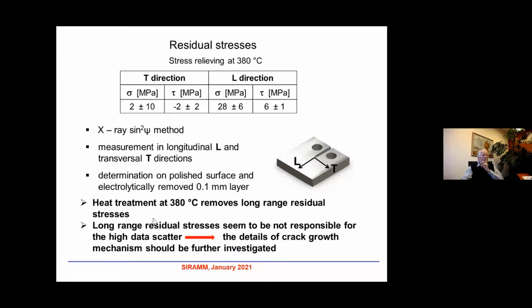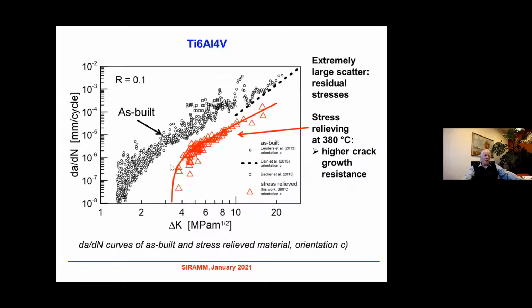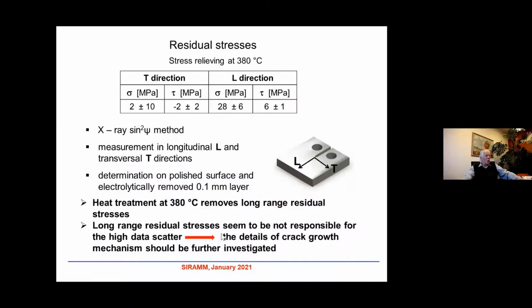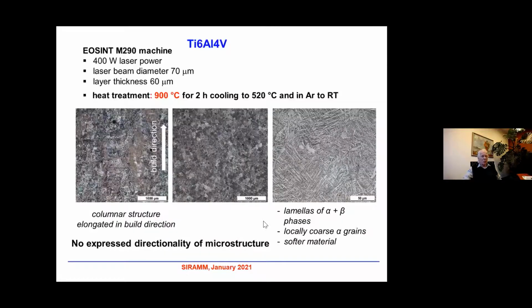So it means that the heat treatment at 380 centigrade removes long-range residual stresses, which is good. It means that the component is not deformed if we remove it from the platform. Simultaneously, it seems that explaining this shift by means of residual stresses, which was done in the literature, is perhaps not okay. Long-range residual stresses seem not to be responsible for the high scatter of data. It means that the details of the crack growth mechanism should be further investigated in this material. It is a little bit of an open question now.